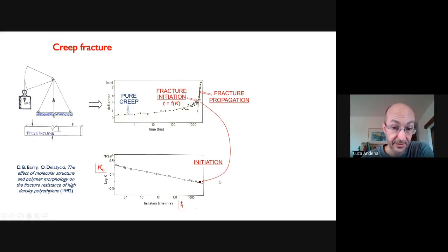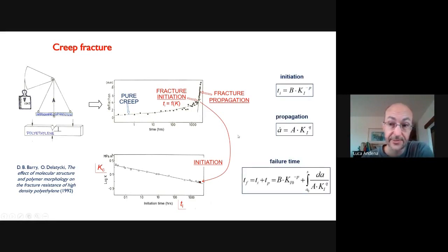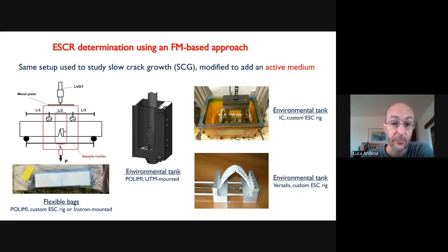So you typically obtain this kind of relationship, and it turns out that power laws can describe quite well the relationship between the existing parameters. And an important aspect of this approach is that you can not just rank the materials, but also make predictions on lifetimes of a given product once you know the initial defect size and the applied conditions in terms of K. Now, of course, you can use this also to study the effect of the environment, provided you have some way of adding the environment in your testing setup.